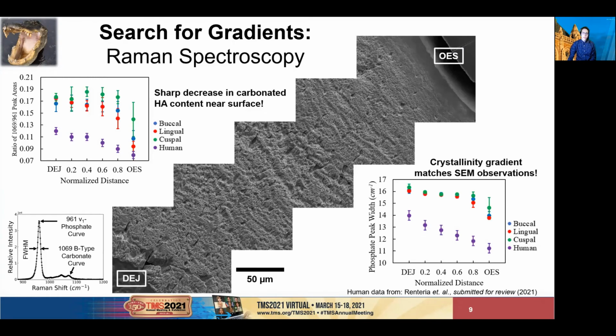To reinforce our spatial understanding of the enamel, we conducted Raman spectroscopy in the same positions as the nanoindentation. The 2 features we will be considering for this analysis are the 961 phosphate peak and the 1069 carbonate curve. Following our experience and the guidance of literature, comparing the ratio of the area under these 2 peaks reflects the amount of carbonate substitution that has occurred in hydroxyapatite.